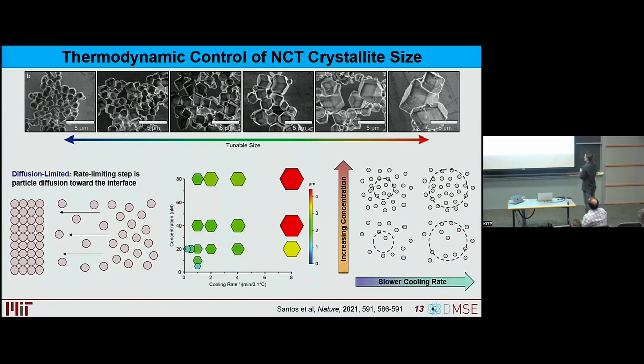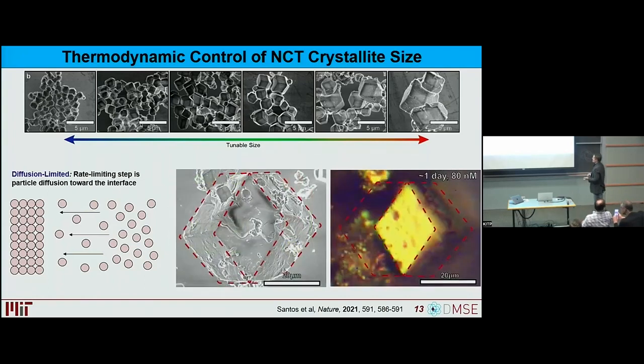So if we increase the concentration or we slow the cool rate, we basically have a larger pool of particles to pull from when we actually have a nucleation event. And so this helps explain why we actually have larger crystallites when we have higher concentration. This is something I'll come back to in a minute. But the key take-home here is it allows us both to understand and study a lot of the fundamentals of nucleation and growth by looking at this very rapid nucleation process. It also allows us to make fairly large crystallites.